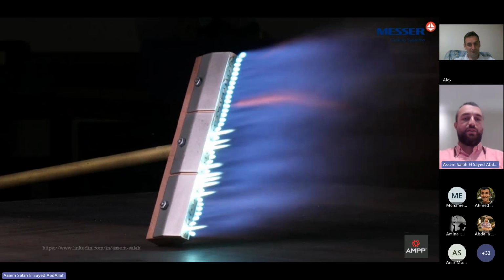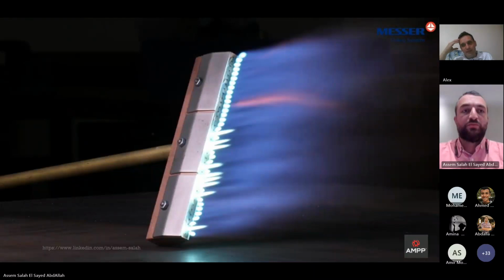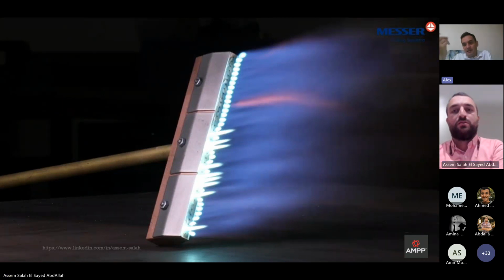Mr. Ax, did you ever see this way before? I've seen it once, but it was not effective at all. At one yard where normal blasting was not allowed, they brought these machines. They spent a lot of diesel, and the productivity was poor. They wanted to remove maybe 2 or 3 millimeters of old coatings, quite thick.